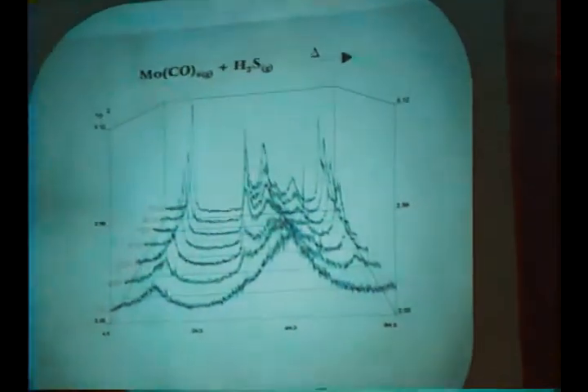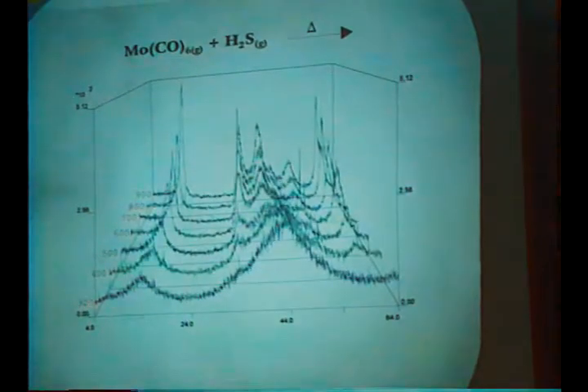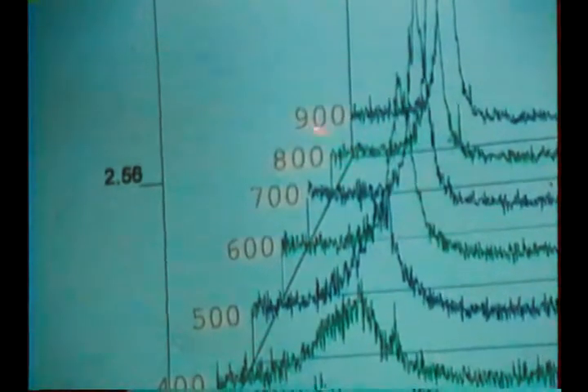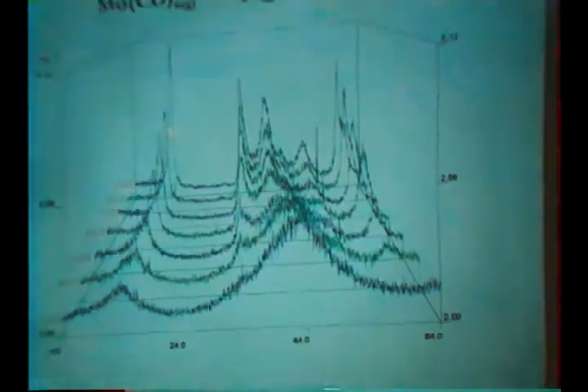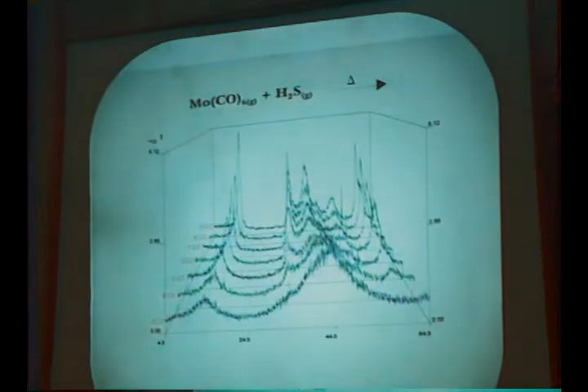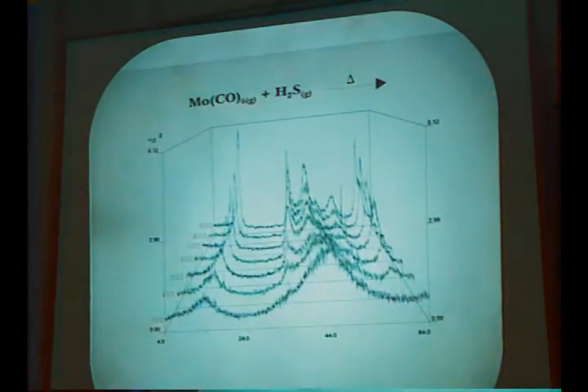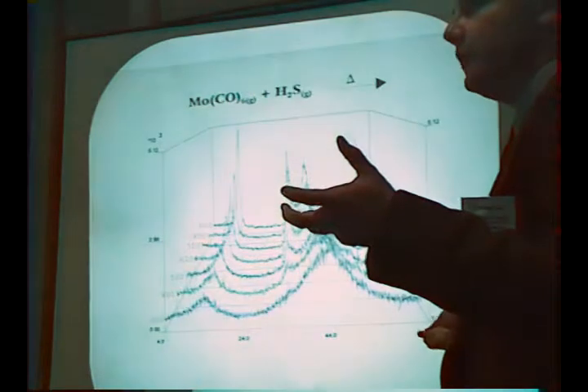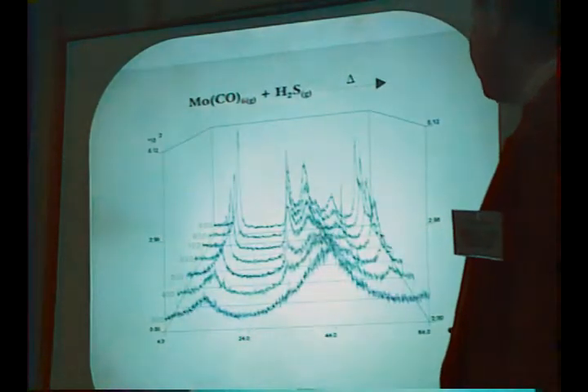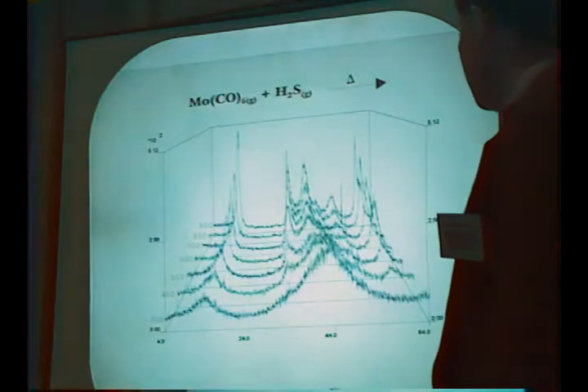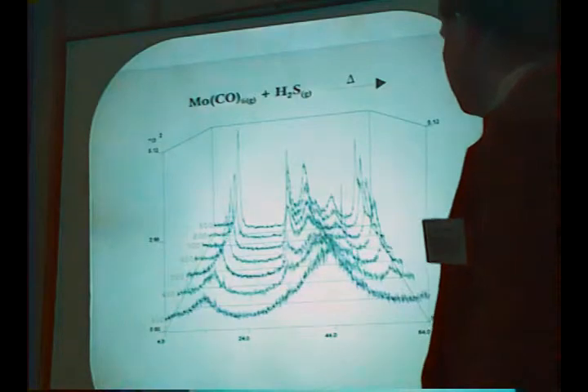Here we have the X-ray powder diffraction data for the materials I presented on the previous slide. Again, going from 300 degrees centigrade up to 900 degrees centigrade. What you notice quickly is the change in crystallinity as the temperature is increased. Essentially, the material at 300 degrees centigrade has very broad peaks indicative of a small particle size, and we know that it's actually indicative of a completely different material being prepared at 300 degrees. So the molybdenum disulfide is not prepared at 300 or 400 degrees centigrade. It doesn't come about until 500 degrees. And you can kind of see that in the X-ray diffraction pattern.